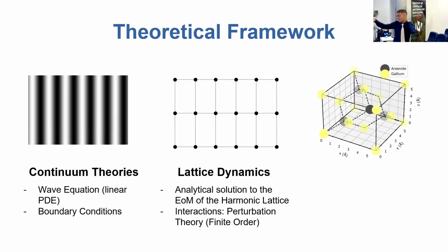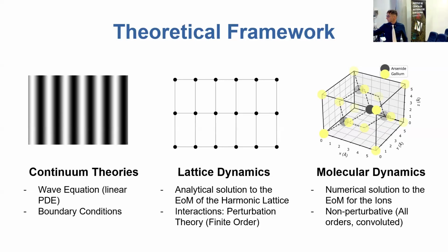Then the last means of describing thermal transport, in our case, is provided by molecular dynamics. In this case, one chases the numerical solution to the equation of motion for the ions and solves them numerically. This is a very good means of describing thermal transport as well, because it allows us a very direct comparison with the experiment, meaning that we are concretely just realizing in our simulation what we would do in the lab. But it has a counterpart somehow, that is, it is completely convoluted. This approach is non-perturbative, so it includes all orders in perturbation theory, and we cannot switch on and off specific processes according to our will.